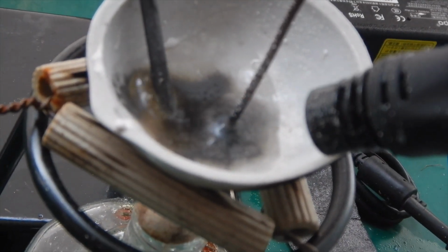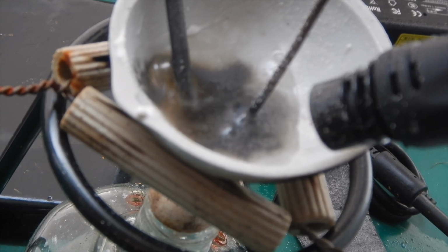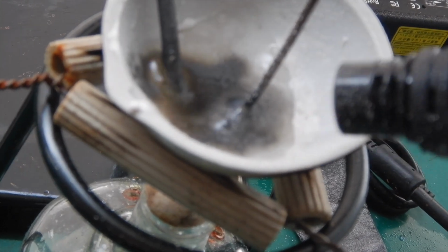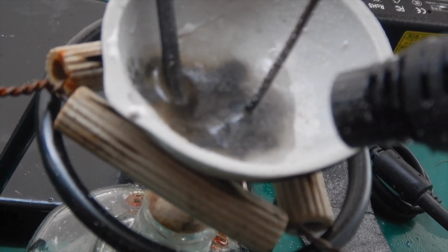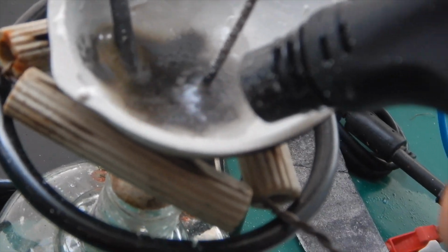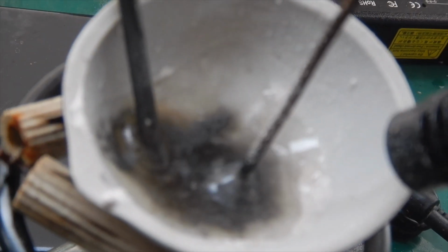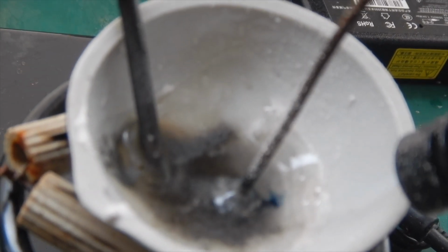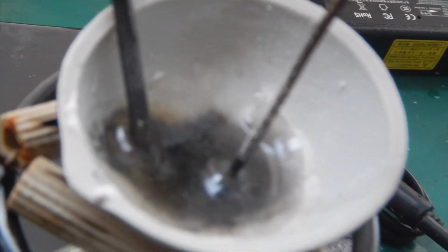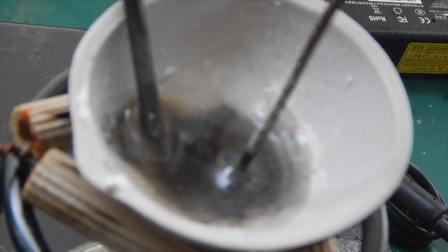I tried blasting the lithium with a blowtorch, and it didn't burn, but a vibrant red flame color can be seen, characteristic of lithium. Using the blowtorch, I melted some salt solidifying on the sides of the dish. At this point, the cathode started producing a dark blue color that immediately reminds me of lithium dissolving in ammonia. Maybe it is actually something related to solvated electrons and complexes? I had no idea. Please tell me in the comments if you have any thoughts.